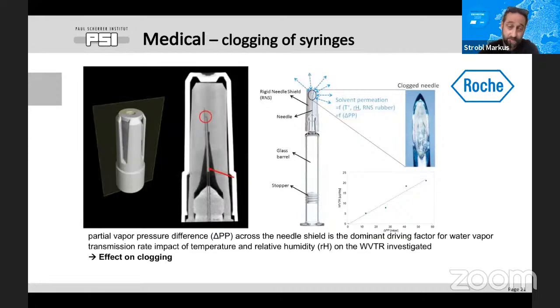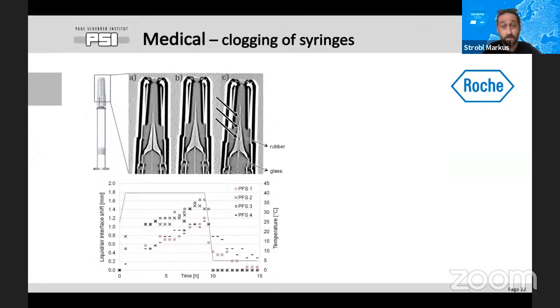And in this case, they had their own project on this already with a scientist. So we could also publish this work, as you will see later. But most importantly, we could show that we can very well not only see the filling state of these needles, but we can also see when they're clogging, when it is crystallizing and cracking. So this allowed us to make studies on the closed syringes in their natural environment and after storage and under different conditions of storage to investigate the effect of clogging in order to avoid it.